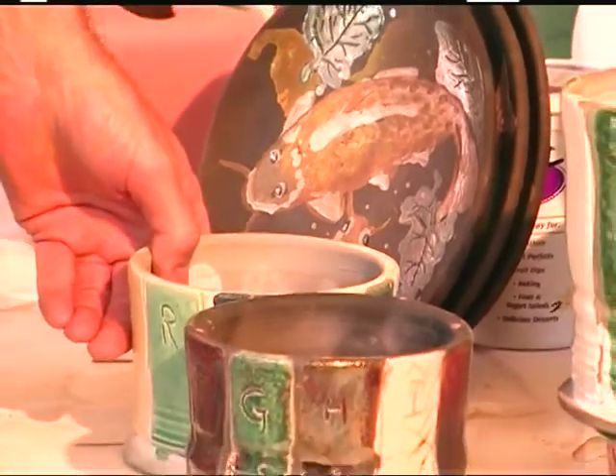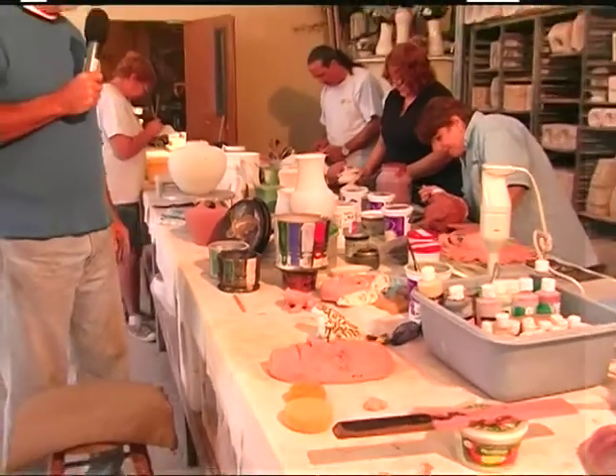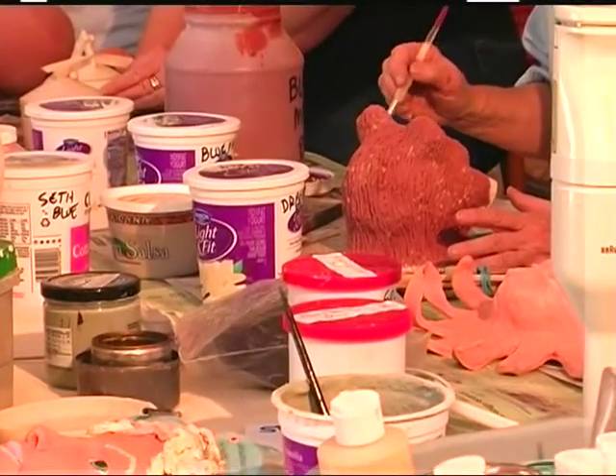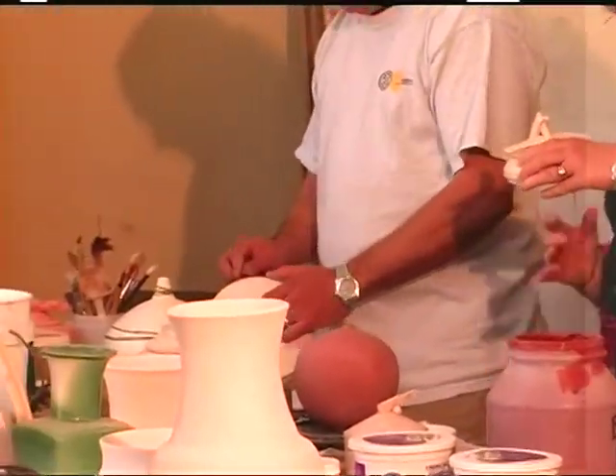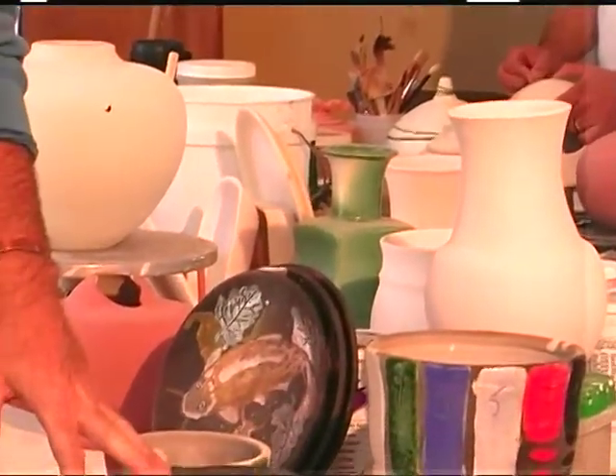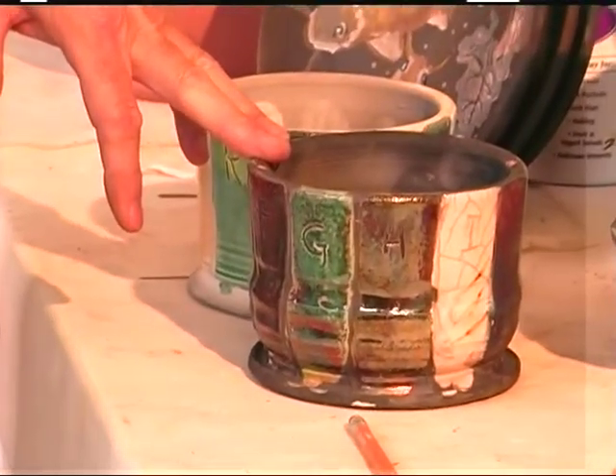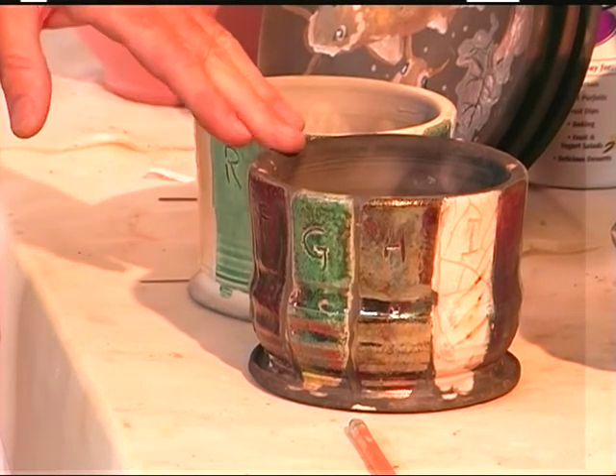And today what we're doing here is we're doing decorating in preparation for a firing that we're going to do in a couple minutes. And you can see folks that are actually painting on sculptured pieces and thrown pottery and using different colors. Now, different colors in the mixture of the glaze will come from different metals or chemicals that are in there. You see, the blues generally come from a cobalt carbonate. Greens will come from a copper carbonate. Some yellows and browns may come from rutile or iron oxide. And generally a mix of Gerstley borate and colemanite will give you a clear or a white